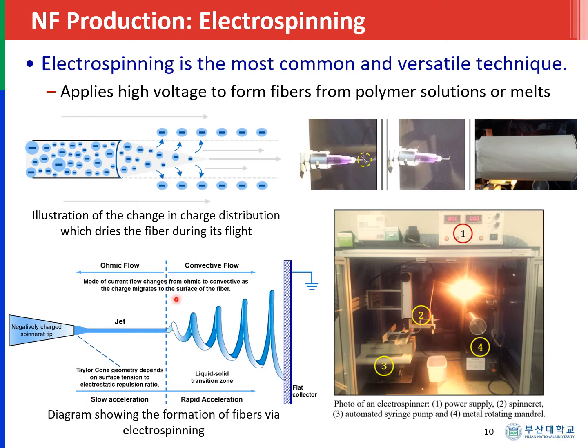So this region is characterized by ohmic flow, and there is slow acceleration. Then from this part, the charged jet now transforms into fibers. And as the fibers fly from this region going to the collector, the solvent molecules rapidly evaporate. Hence, this region is characterized by convective flow and rapid acceleration, or specifically a rapid liquid to solid transition. Because the charged jet of solution, which is liquid, will transform into fibers. So fibers are solid once they become dry.